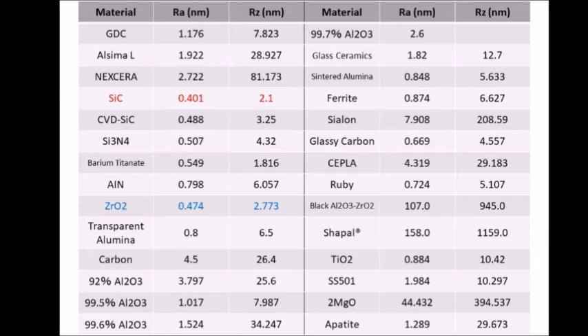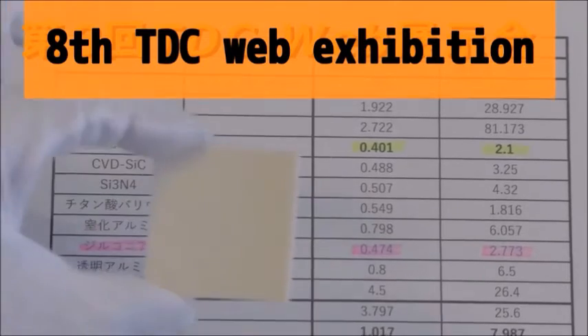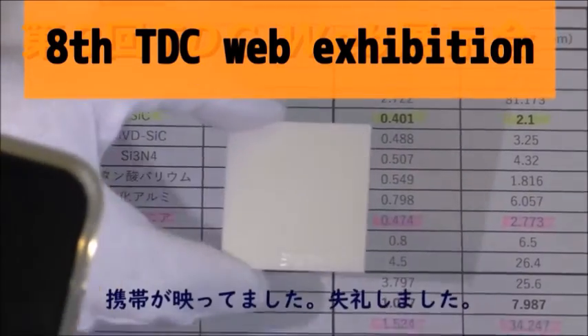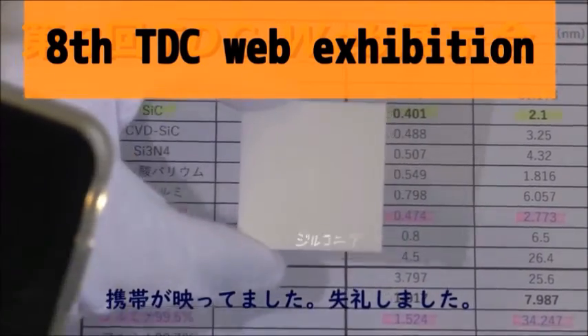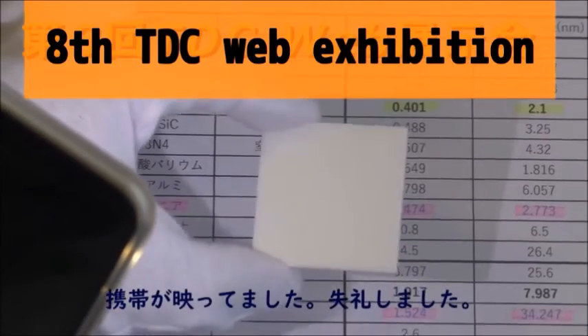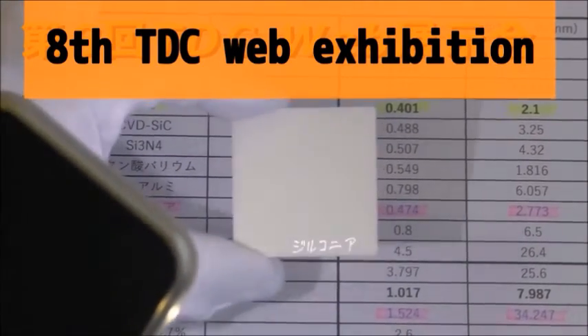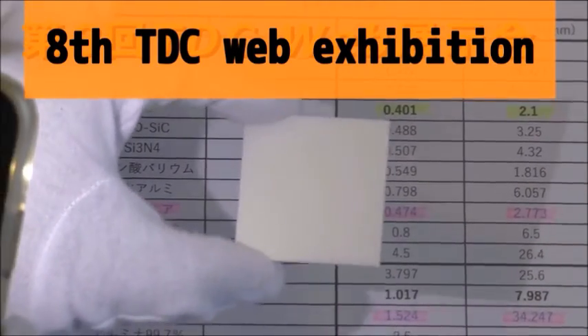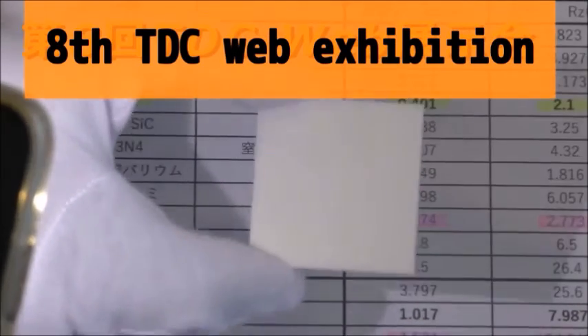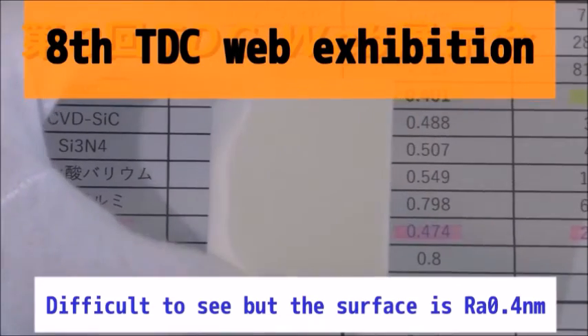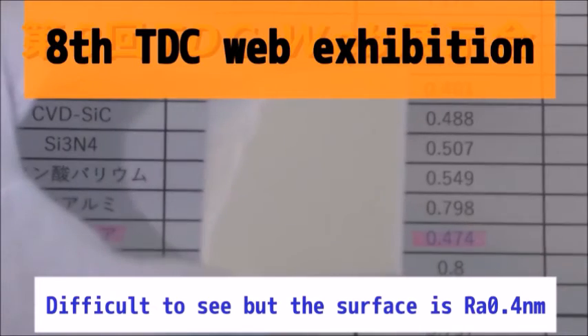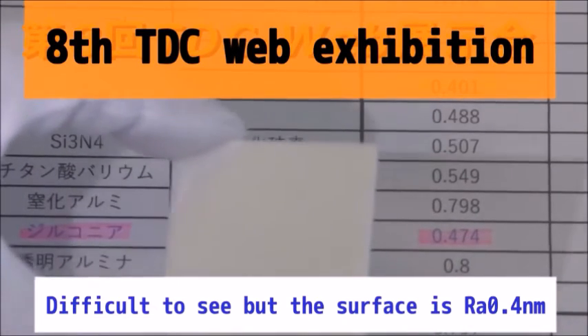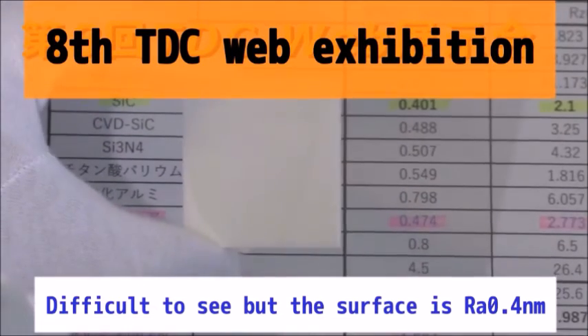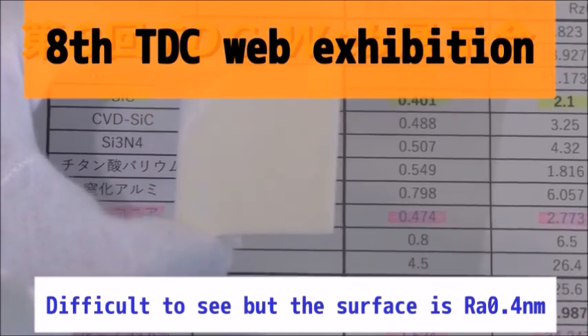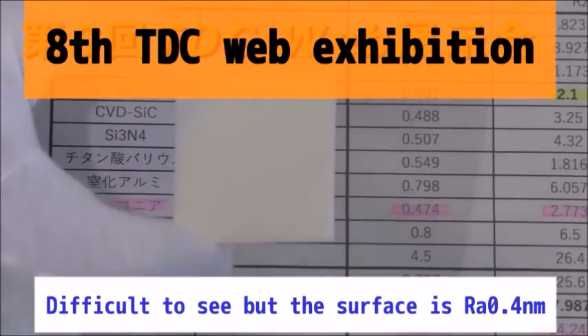I have a sample of zirconia, so let's take a look. Sorry for my cell phone in the way. This surface is before polishing, the surface that the material itself has. This surface is after polishing. It looks shinier than before. Roughness is Ra 0.4 nanometers and Rz 2 nanometers.